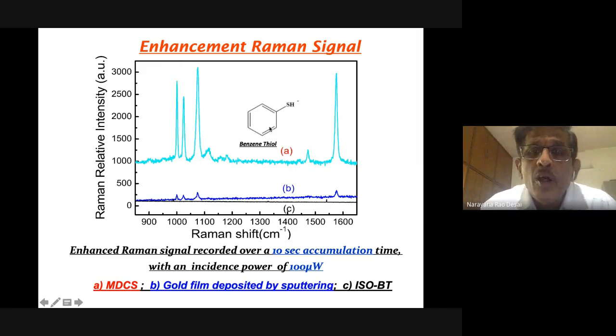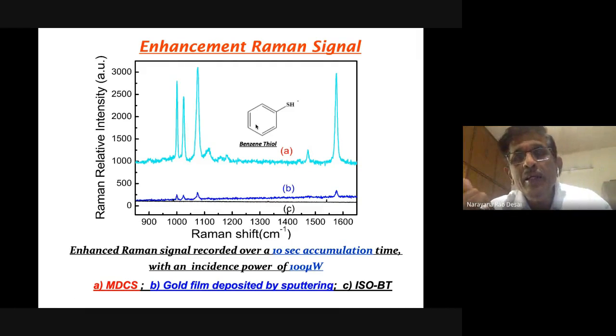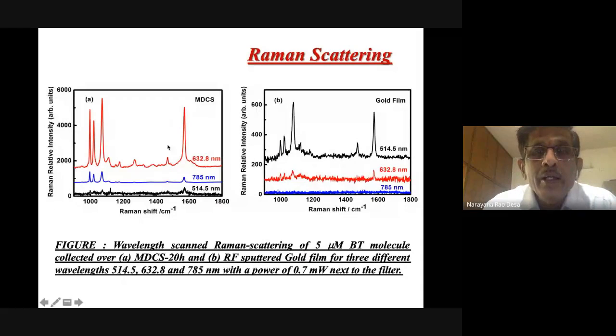That is because you have got both surface plasmonic as well as photonic reflection. That means reflectivity is very high, and also you have the effect of the plasmonic structure. But there is another thing when you record at 632, 785 and so on. The Raman should be strong with 5145 compared to 632, but here it shows very weak. Whereas if you put in a gold film, it exactly follows the regular Raman scattering, omega to the power of 4. Because omega is smaller here it is weak, becoming stronger and strongest with 5145.